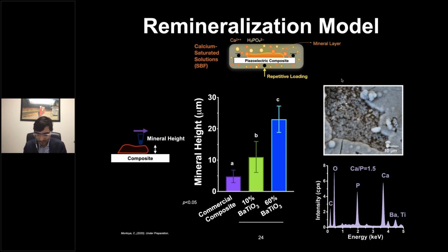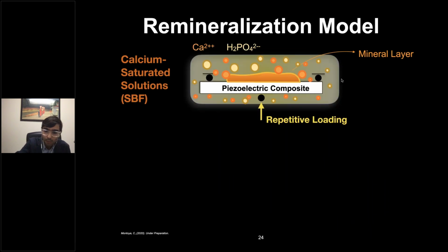We're doing some visual analysis—this is SEM imaging. The white things you see here are layers and layers of minerals being formed on the surface. If we do elemental and chemical analysis on these materials, we begin to see peaks of calcium and phosphate, which are expected since that's what we had in the liquid solution initially. It's very exciting that just by activating the charges, we're able to form these new minerals.